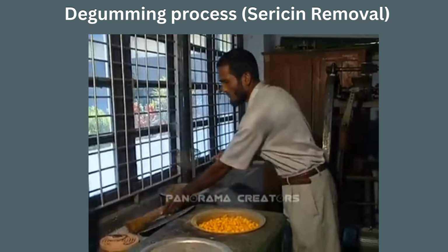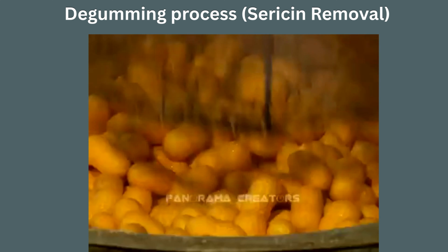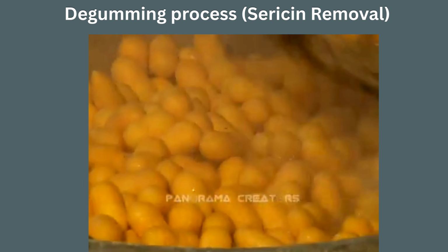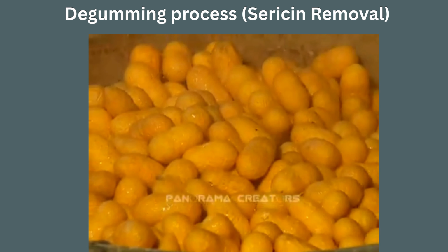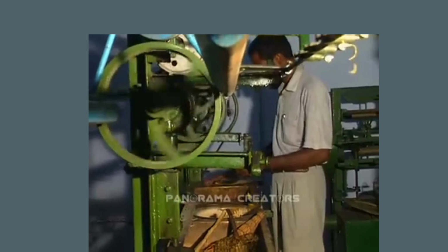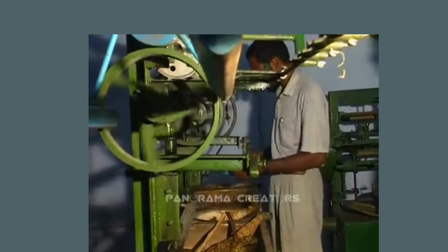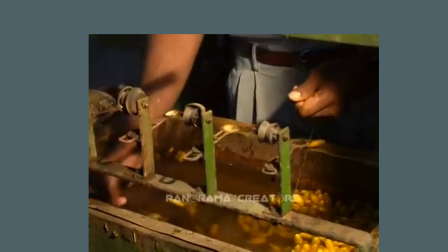Preparation and regeneration of silk fibroin. Dissolution of fibroin. Degummed silk fibers are dissolved using chaotropic agents such as lithium bromide, calcium chloride-ethanol-water systems, Ajisawa's reagent, and zinc chloride. The resulting solution is dialyzed to remove salts, yielding an aqueous fibroin solution.